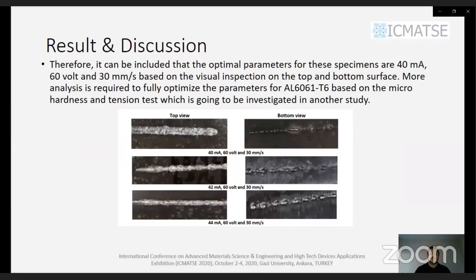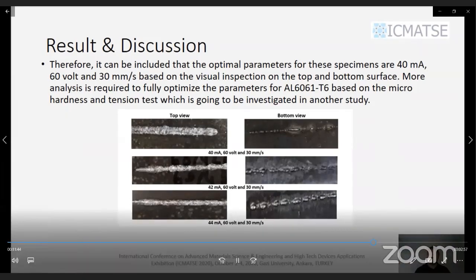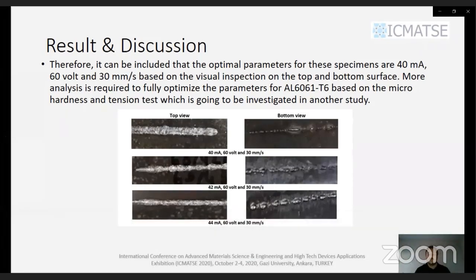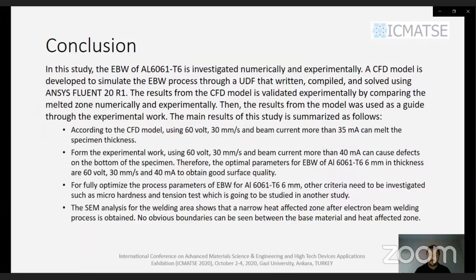Therefore, it can be concluded that the optimal parameters for the specimens are 40 mA, 60 volt, and 30 mm per second based on the visual inspection of the top and bottom surface. More analysis is required to fully optimize the parameters for aluminum 6061 T6 condition based on the microhardness and tension test, which is going to be investigated in another study.